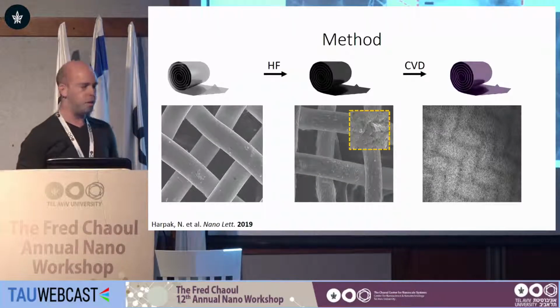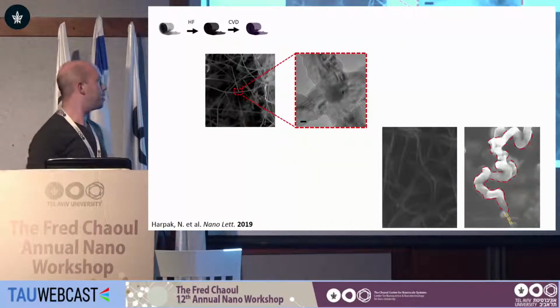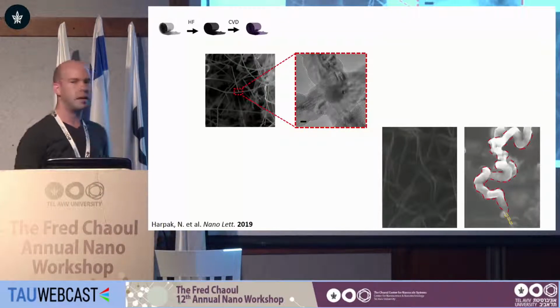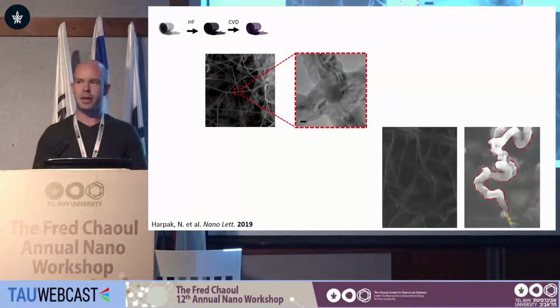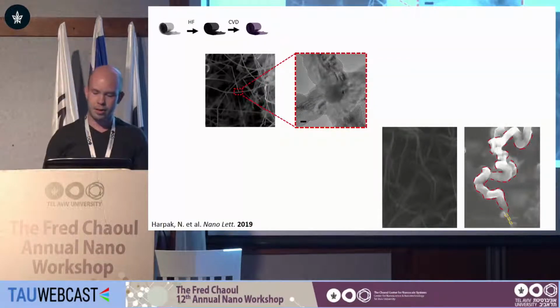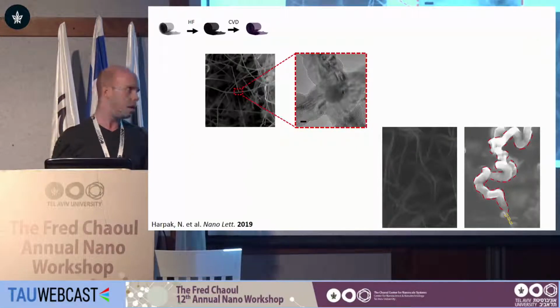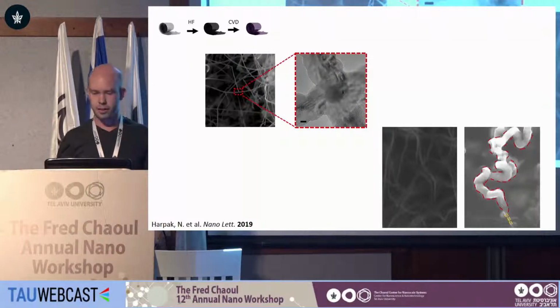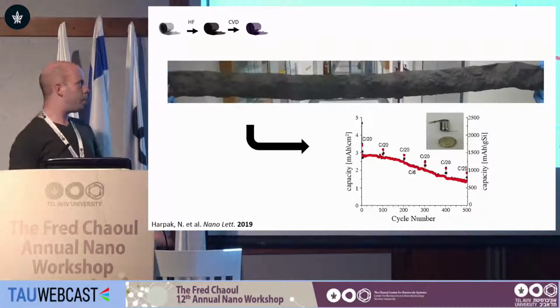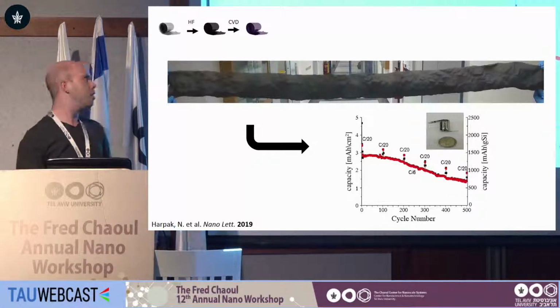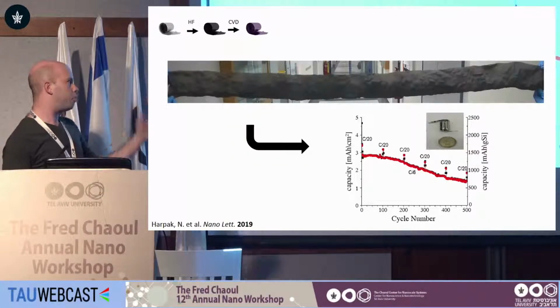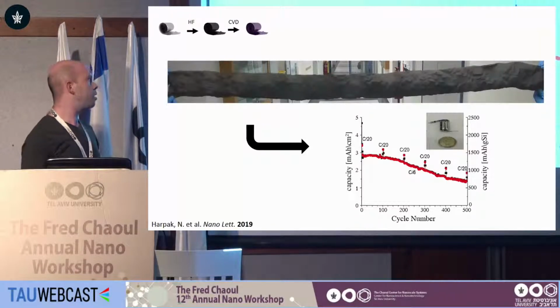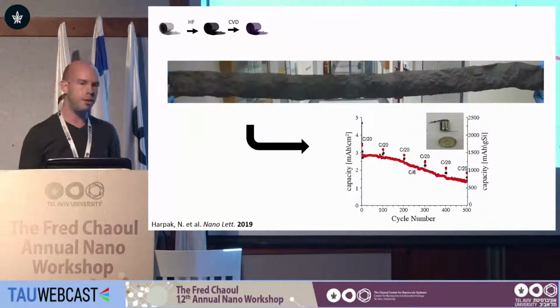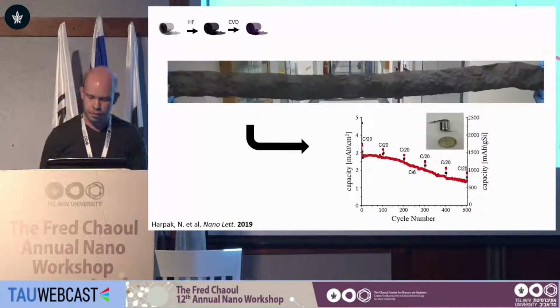What's special about this substrate is that it has increased mechanical stability. And it doesn't delaminate from the surface because it has a short section of nickel silicide that doesn't expand as much as the other elongated silicon structures. And what we did in our lab is very easy to upscale, and we managed to make around 2 meters of the composite anode and employ it in a commercial battery, which is currently being progressed.